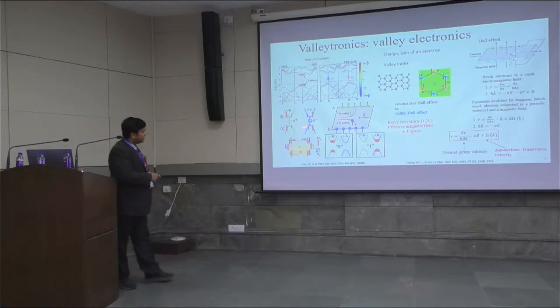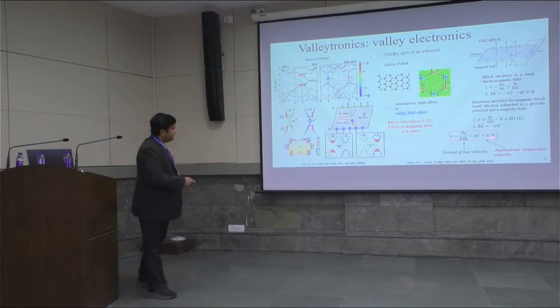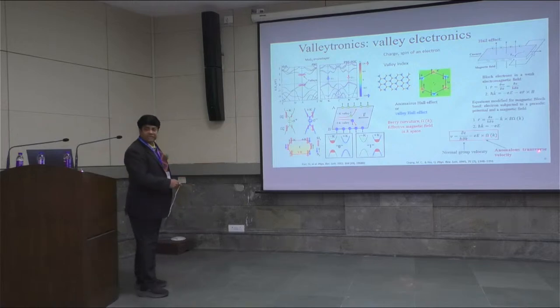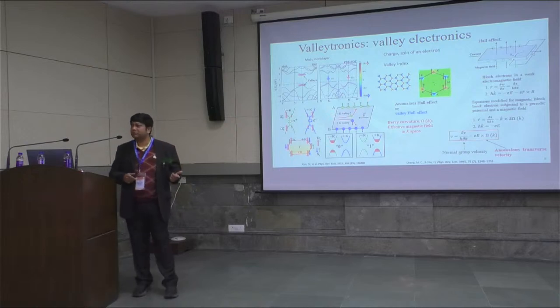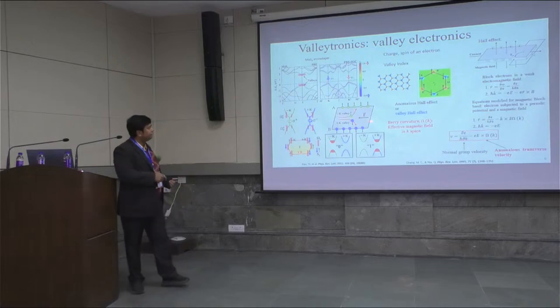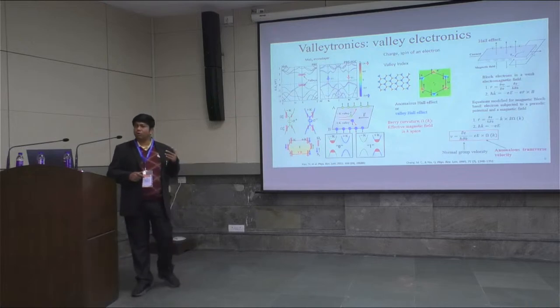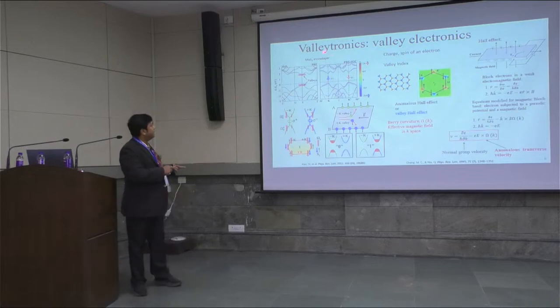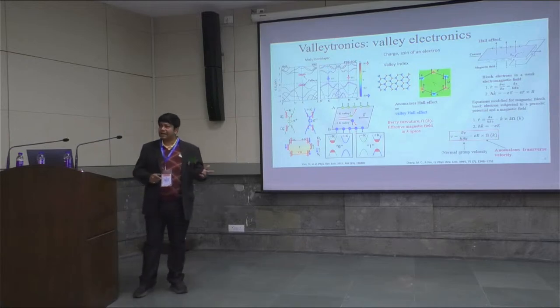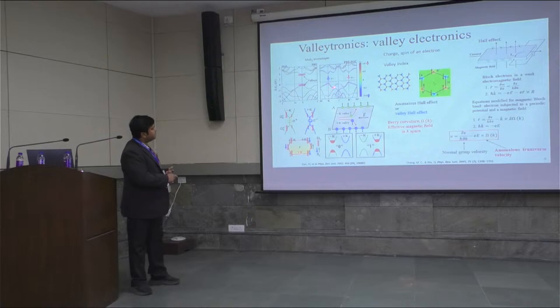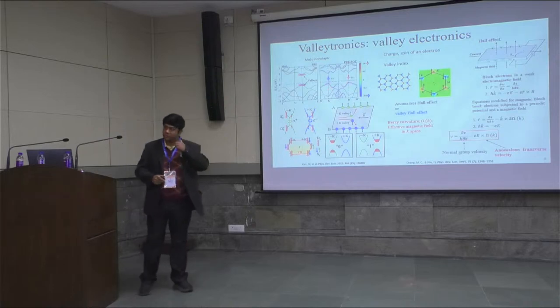So the carriers in this valley, upon the application of the in-plane electric field, acquire this anomalous transverse velocity. And the carriers in this valley undergo a Hall effect, which is called the anomalous or the valley Hall effect. And very few materials are experimentally known which exhibit the valley Hall effect. Those materials are mainly MoS2 like, which show a large Zeeman type spin splitting at the valence band and a very small splitting at the conduction band.